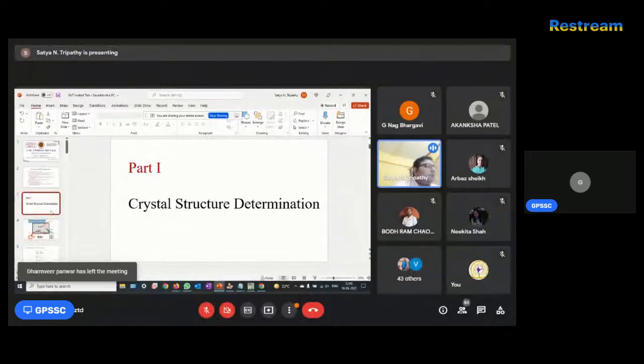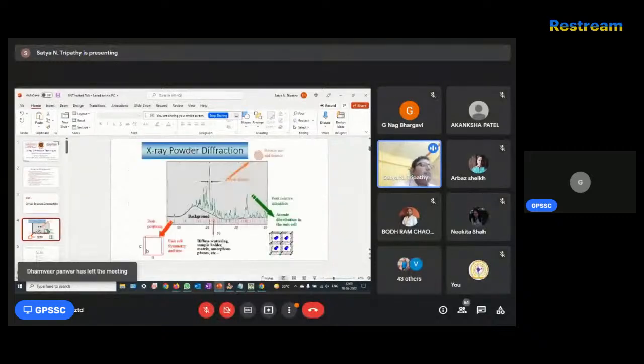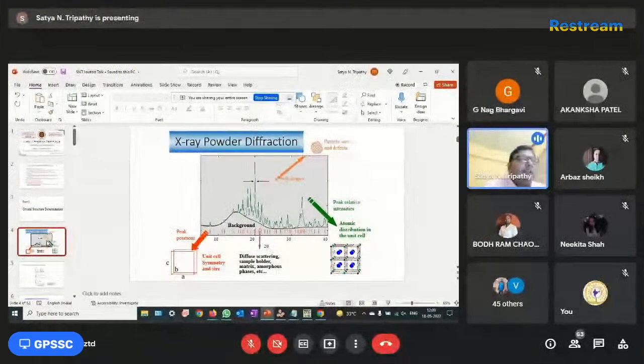Now I'm going to show you a single X-ray diffraction pattern here. As you can see, this is an X-ray diffraction pattern. In an X-ray diffraction pattern there are so many peaks. All the peaks vary from 10 degrees to 40 degrees here. There is a background, there are peak positions, peak shapes, and peak intensities.